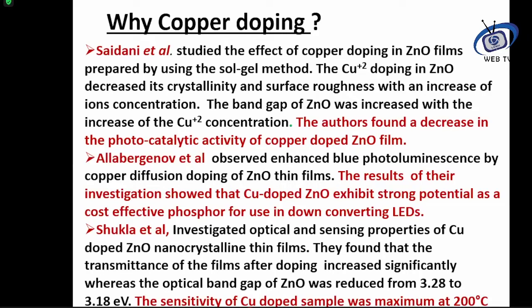And then Shukla et al. published. They worked on the sensing property of the copper doped zinc oxide crystal, and they found that the transmittance of the films increased significantly after doping, whereas the optical band gap of the zinc oxide reduced from 3.28 to 3.18.